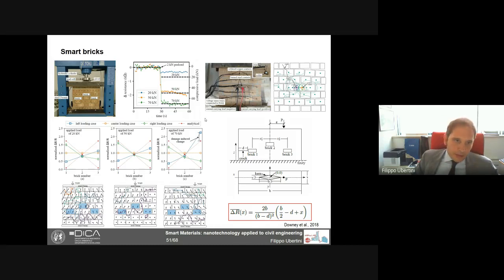We measure these results at 20 kilonewton, 50 kilonewton, and 70 kilonewton. We see that from 20 to 50, there is no change in the results. And this is something we expect from the theory if the material is in the elastic range, even if it's cracked, but it's in elastic conditions under compression. We do not have any sensitivity of the normalized change in resistance divided by the change in resistance at the mid brick to the load.